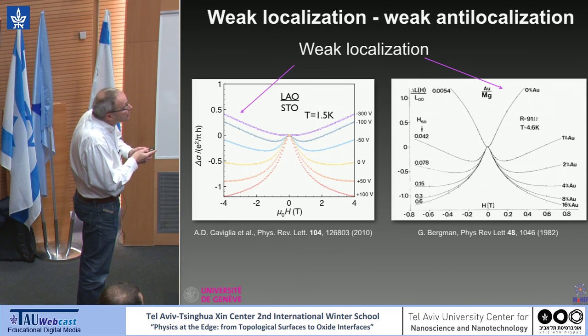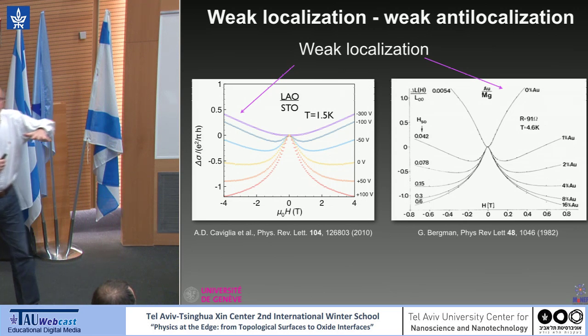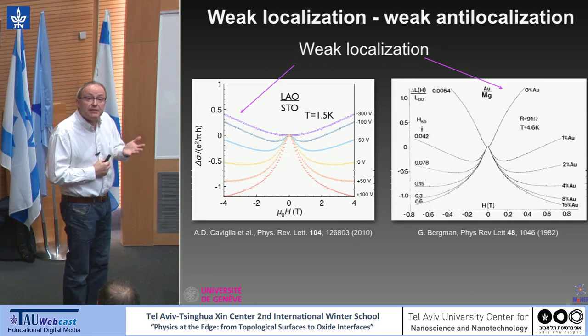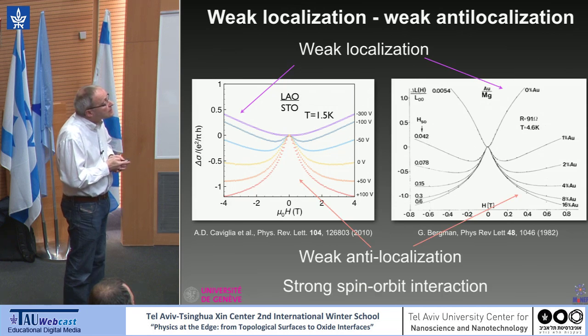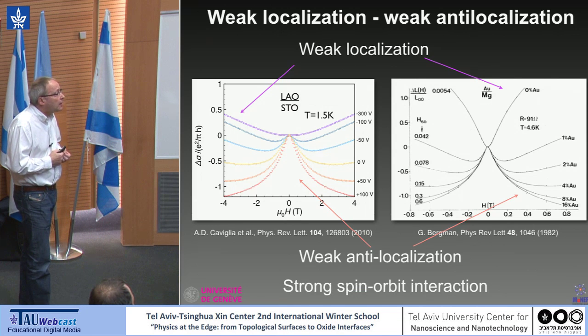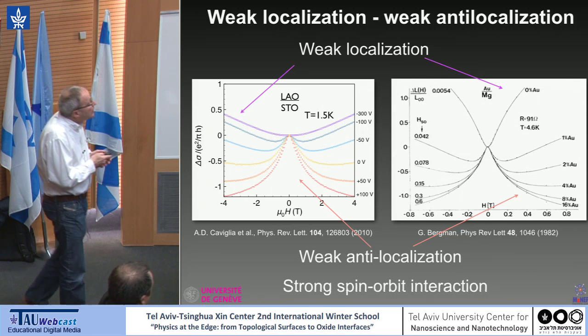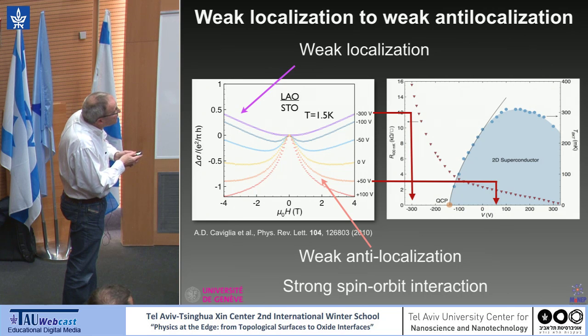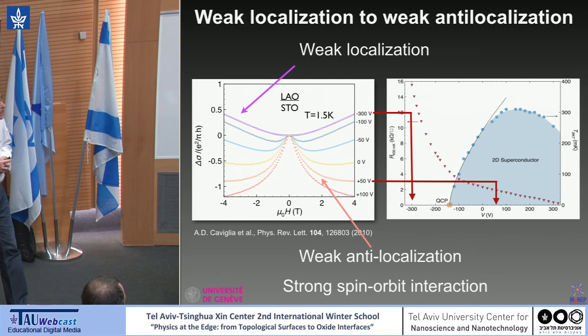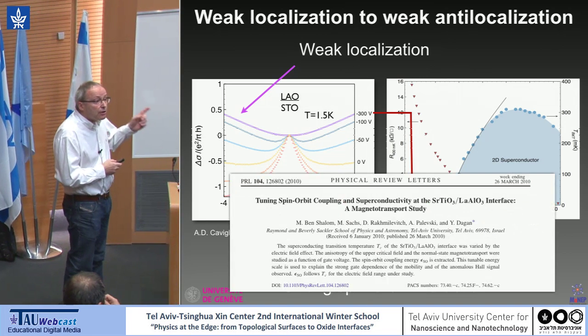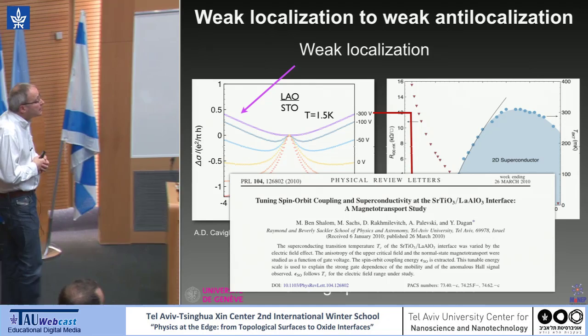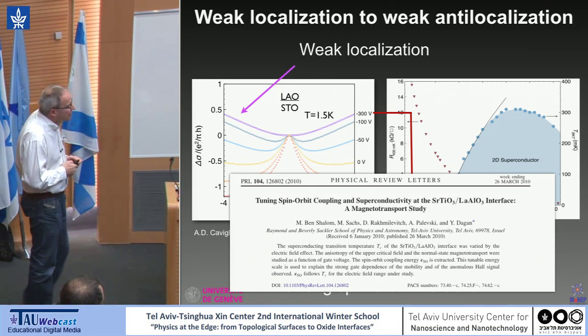This is also what was observed when gold was put on the surface of magnesium. Gold is a strong spin orbit scatterer, and this is called weak anti-localization, and this is a signature of a spin orbit interaction. In this region of the phase diagram we see this behavior, and when you move here, you see this weak anti-localization behavior. From this analysis, we can extract the spin orbit strengths. Let me just mention that there has been a lot of work here in Tel Aviv in the group of Yoram Dagan with Alex Palevski on the same type of studies, but using a slightly different technique to extract the spin orbit strengths.